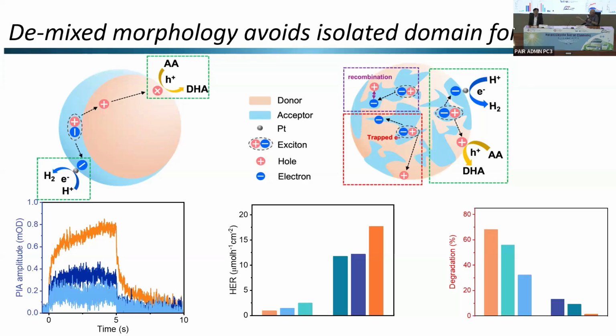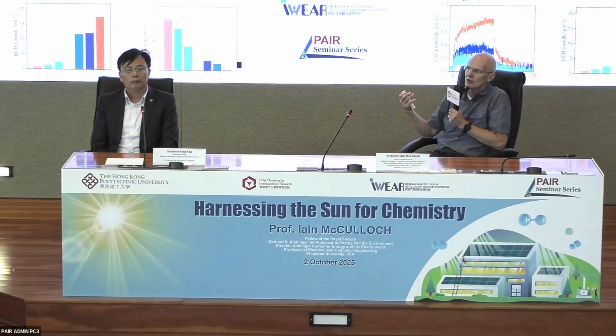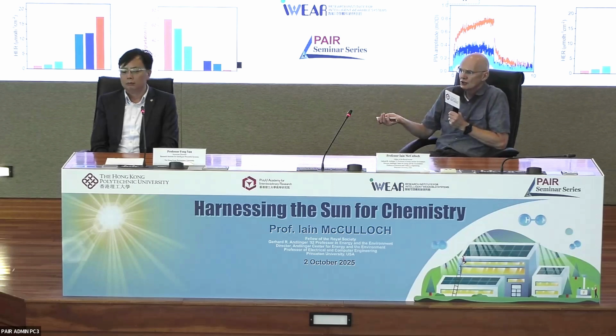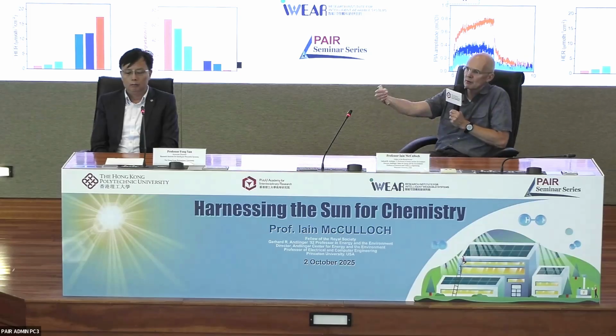One thing that we can see is that with most non-fullerene acceptors, if you trap an excited electron and there's no way for it to reach the co-catalyst on the surface, the likelihood is that it's going to undergo some unwanted chemistry that leads to degradation. So if you have a demixed system, like a broken core-shell or a Janus-type structure, you reduce the isolated electrons in your acceptor, and that dramatically improves the stability. To what degree, we're still working on this, but we know that's a step in the right direction.